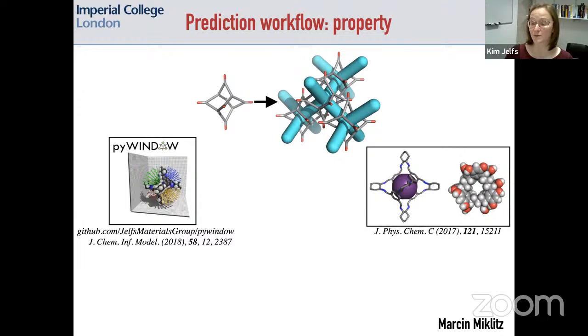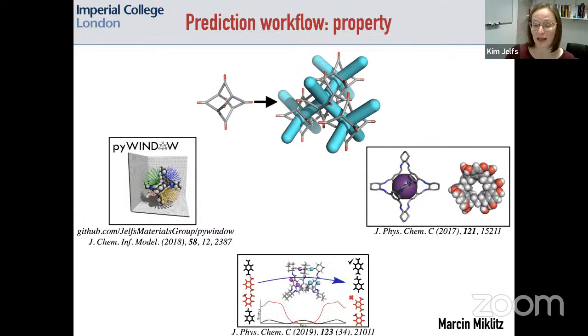And that identified a new system that was potentially promising, the one shown on the right, the Noria water wheel. And our experimental collaborators then synthesized it and tested it for xenon-krypton separation and found that indeed it did have the performance we were expecting. And we've done similar approaches, also funded by industry, looking at separations of hydrocarbons and xylenes as well.